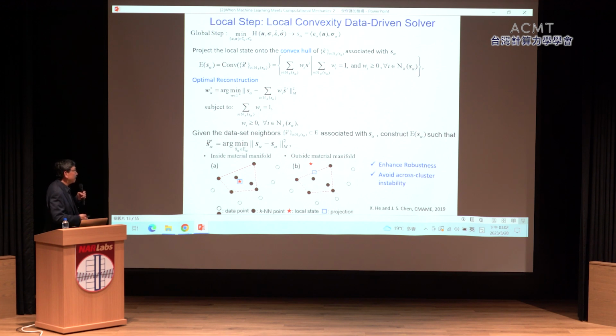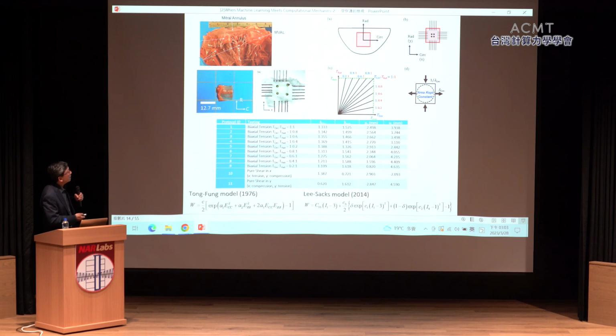This has significantly enhanced the stability of the data search. In the earlier work, for example, by the group of Ortiz, they simply look for the data point that is closest to the physical state. But that makes the algorithm, well, very simple, but the results are too sensitive to the noise in the data and too sensitive to the outliers of the data. Having this convex hull, with the coercivity or convexity, it really stabilizes this whole process and it becomes more robust. Okay, so here is a test.